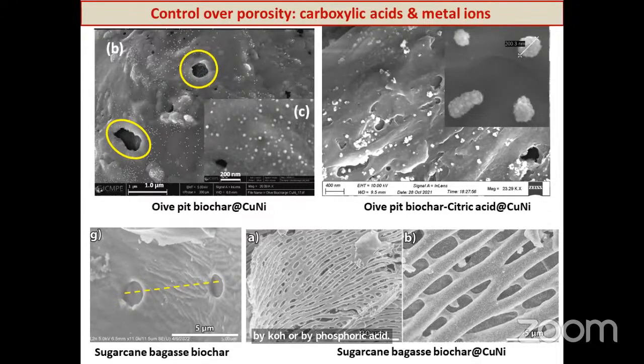We abandoned these routes and preferred, for example, to work on maceration and mechanical grinding, and also use the precursor of the immobilized nanocatalyst to provide a very porous structure. You can see here what I have shown earlier, the olive pit, but the olive pit does not provide a lot of porosity. With the same protocol applied to sugarcane bagasse, the pulp of sugarcane, we have a porosity, a structure like a fishnet structure that is induced by nickel.